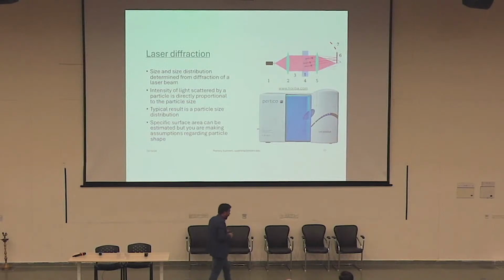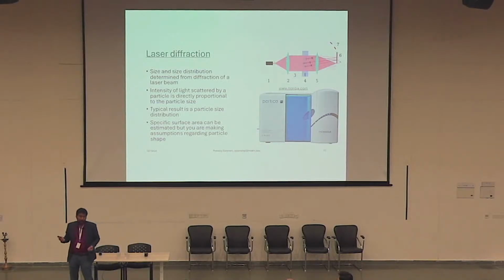So the typical result is some kind of a particle size distribution. And of course, you can actually estimate the specific surface area from a size distribution. However, these sort of measurements always assume that the particles are spherical. You can make corrections if your particles are not spherical, but that means that you need to know what the shape of your particle actually is. This is a very standard test. How many of you have used laser diffraction?